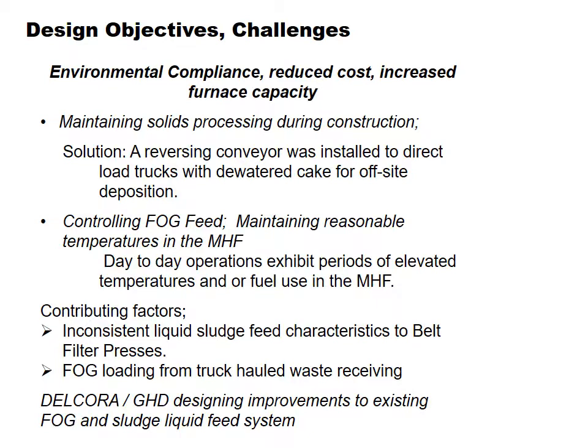The next thing is DELCORA takes in FOG waste and they thicken it. But then they put it in sludge holding tanks. It floats to the top. These tanks are not well mixed. When they pump these tanks down and they hit the grease, the furnace goes berserk. I mean, it's tremendous heating value with this grease. So we're now working on a project to bring that grease over separately because it also goes through the belt press and causes problems with the belt presses. And so we run it around the belt press, and we're going to drip it into the auger there. Part of the job was to put swing pumps to feed the furnace. We'll get the heating value without the complications.